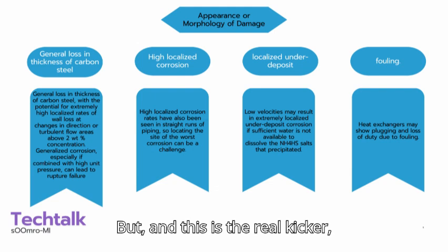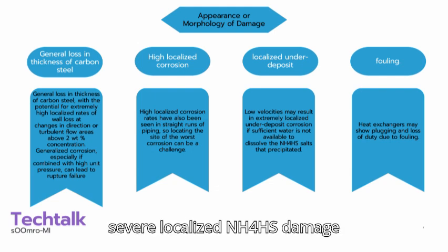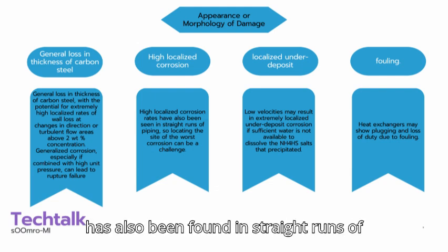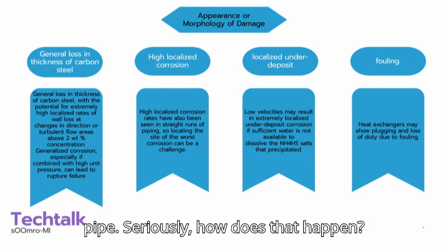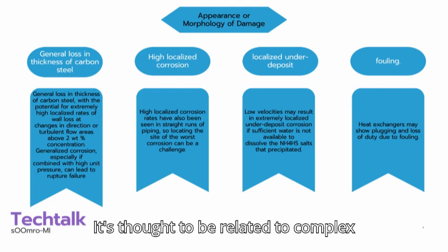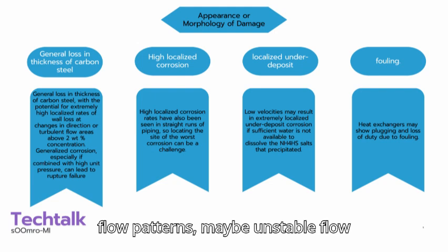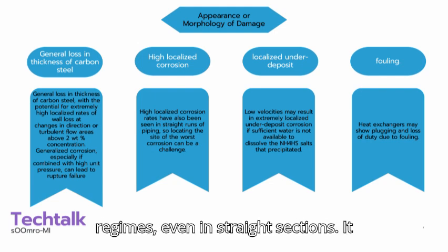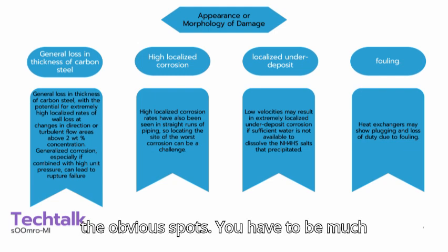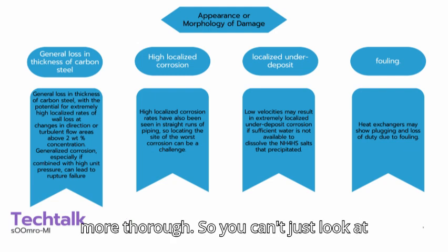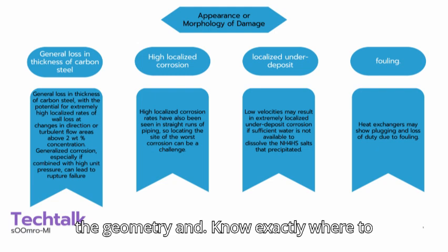But, and this is the real kicker, severe localized NH4HS damage has also been found in straight runs of pipe. Seriously? How does that happen? It's thought to be related to complex flow patterns, maybe unstable flow regimes, even in straight sections. It means you can't just rely on inspecting the obvious spots. You have to be much more thorough. So you can't just look at the geometry and know exactly where to inspect?